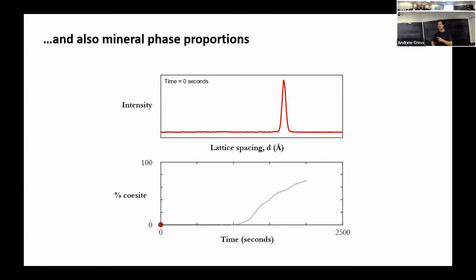The other thing that we can do using the XRD data, and that's particularly important for these experiments, is we can calculate mineral phase proportions for an experiment. Each mineral will produce a distinct set of peaks in our X-ray diffraction spectra. So this is a spectrum for quartz. There are a bunch of other peaks out here, but I've just cropped it around this one main peak. I'm going to play a little movie where, through time, we take this sample and push it up into the coesite field. And so you'll see that this peak for quartz goes away and it's replaced by two peaks, one either side, that correspond to coesite.